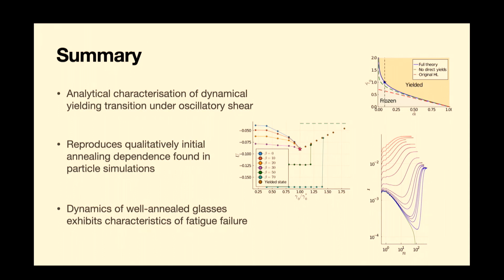Okay, so let me summarize there. What we've done within the model I've shown you is we've analytically characterized this dynamical yielding transition. We can now show that this model that we're using, this disordered Hébraud-Lequeux model, really has a dynamical transition under oscillatory strain. At high strains, you have these yielded steady states. At low strains, you only have frozen states.